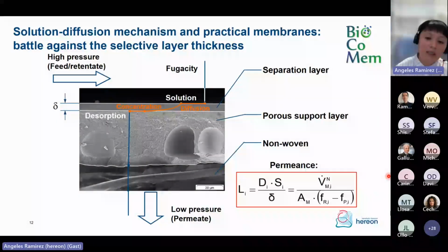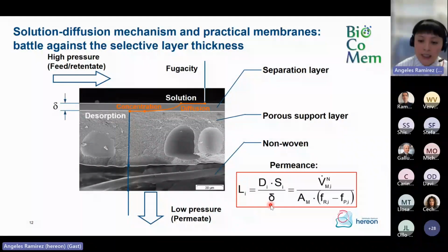Because as we see here in the definition of the permeance for a gas, the permeance is inversely proportional to the thickness of the membrane. That is, the thinner the selective layer, the faster the membrane will be. And this is what we need in order to use this membrane for a practical application.